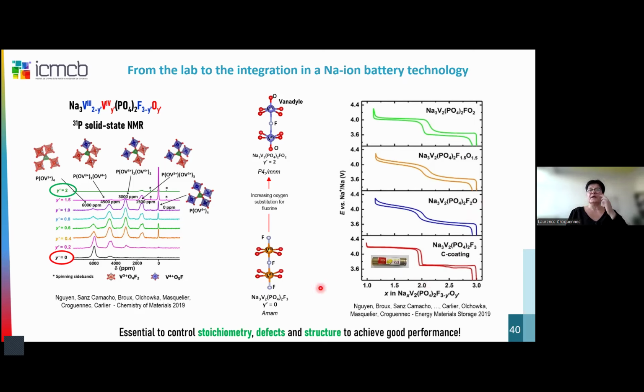And what happens when we have this electrochemical signature here? In fact, we are moving from this bioctahedral unit, vanadium 3+ rich, fluorine along the direction of the bioctahedral unit, and we increase here the oxygen. We have oxygen defects in these materials, and we do not control the fluorine stoichiometry. And in fact, we are oxidizing vanadium 3 to vanadium 4, and in fact, creating these vanadyl-type bonds here.